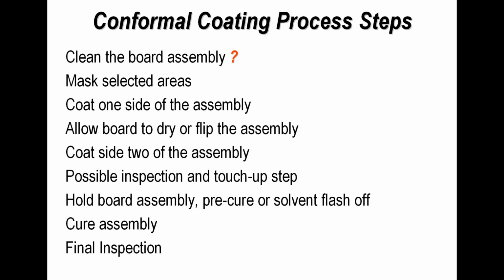Inspection needs to be conducted at some point, and sample inspection is good, but remember, obviously the board is either wet or tacky, so consequently it must be a non-contact method. Next up is there's a hold time, and we're holding the board assembly in the case of solvent to allow the solvent to evaporate off. If you start to dry or cure the conformal coating prior to this operation, then what you'll tend to do is create defects, and probably the most common defect is bubbles in the coating due to fast curing.